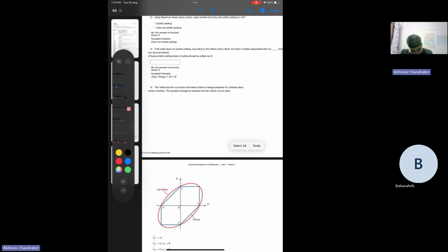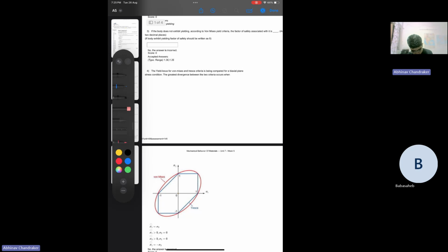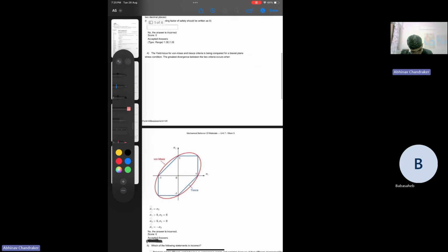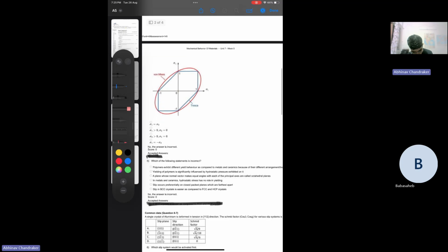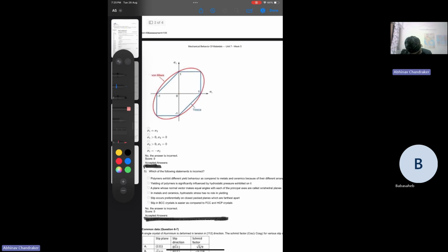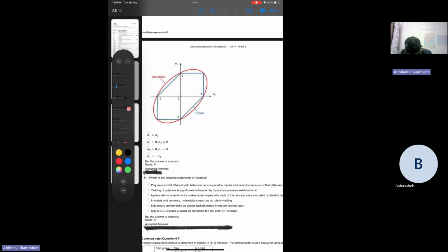The yield locus for von Mises and Tresca criteria is being compared for a biaxial plane stress condition. The greatest divergence between the two criteria occurs when are the two diverging the most? So if we just look at it, they are having the same value at all of these points. There is no divergence at these points. At other points, the Tresca is giving a smaller surface compared to von Mises. And I think in these regions, it is the highest, right?